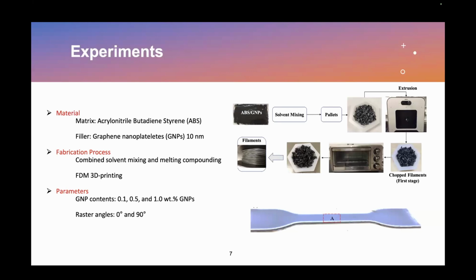Here are the experiments. We used ABS as a matrix and graphene nanoplatelets as the filler. Also, we used the combined solvent mixing and melt compounding to fabricate our filaments and then 3D printed samples. We varied graphene nanoplatelets at 0.1, 0.5, and 1% graphene nanoplatelets. And also we consider two different raster orientations as 0 and 90 degrees.